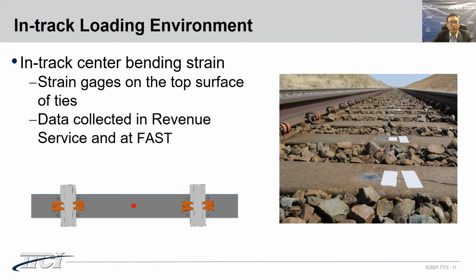So to get reasonable inputs for the laboratory test, we conducted field instrumentation on 4 different types of composite ties to quantify the loading environment. We installed strain gauges at the center top surface of ties, and the bending strain data was collected at various train speeds at different times of day and at both FAST and revenue service test. The ties in each location were selected by the track engineer to ensure severely hanging ties or ties with loose plates were chosen. So overall, these ties were representative of the ties in the test zone.